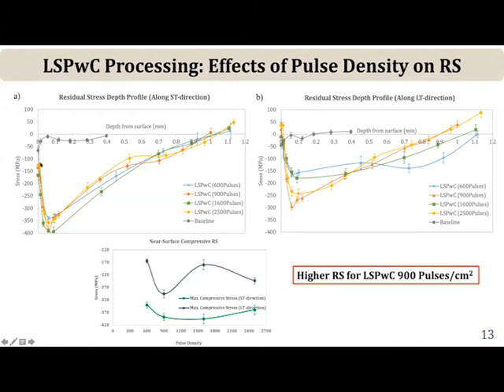But just below the surface, there's a rapid drop, rather a big increase in the compressive residual stress just below the surface. Get about 10-20 microns below the surface, you have a fairly high magnitude of compressive residual stresses to the tune of about -400 in one direction, about -300 in the other direction. And you can see that the depth of compression also goes to about 1 millimeter or so.